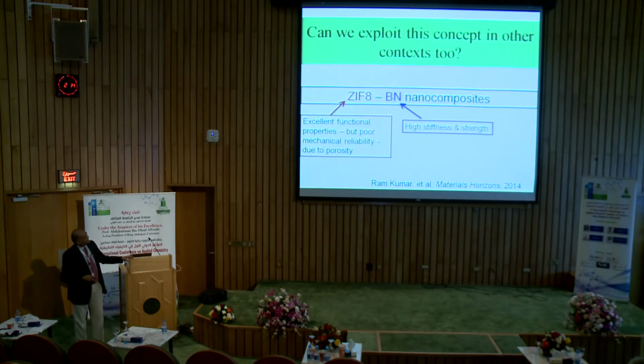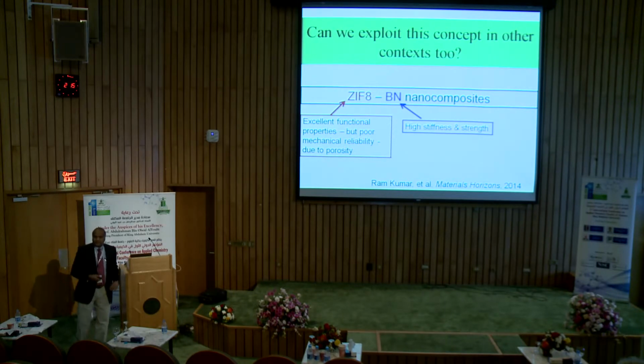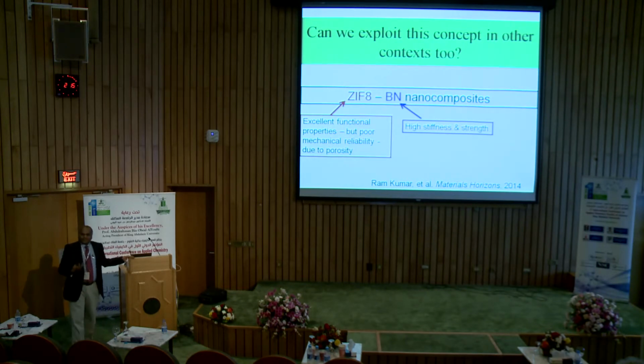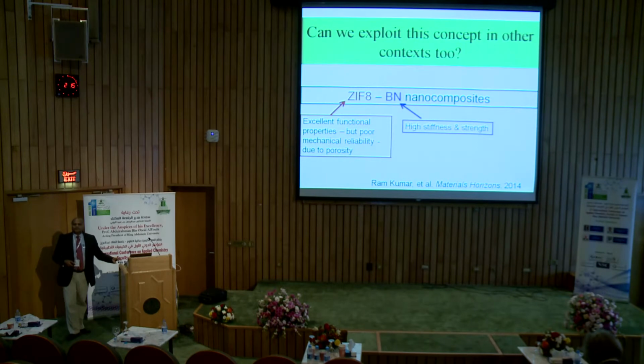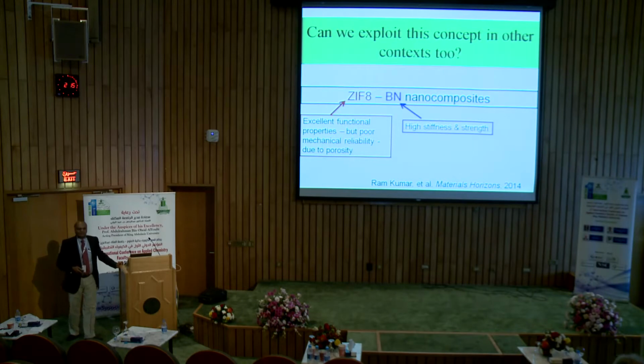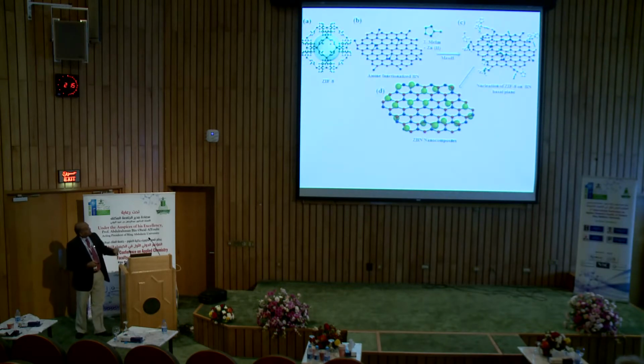Now, this is more recent. This is after listening to this morning's talk on MOFs. For example, MOFs have very attractive functional properties because of the large pores they have, but they are also fragile. So, for example, can I now increase their mechanical properties so that I can deploy them in industry more easily? So we tried to put ZIF-8, which is a well-known MOF, with boron nitride nanosheets. And so the ZIF-8 is grown on boron nitride sheets like this.